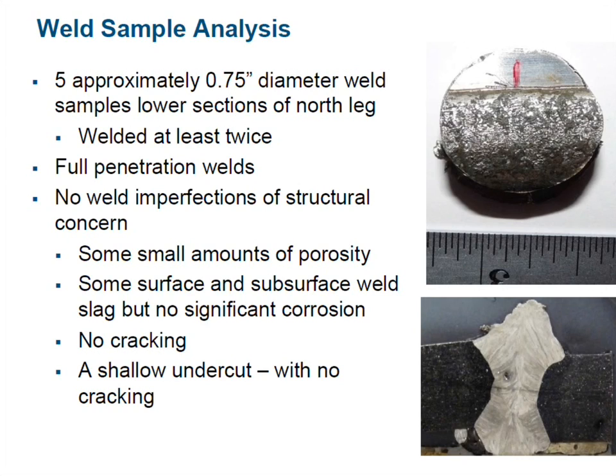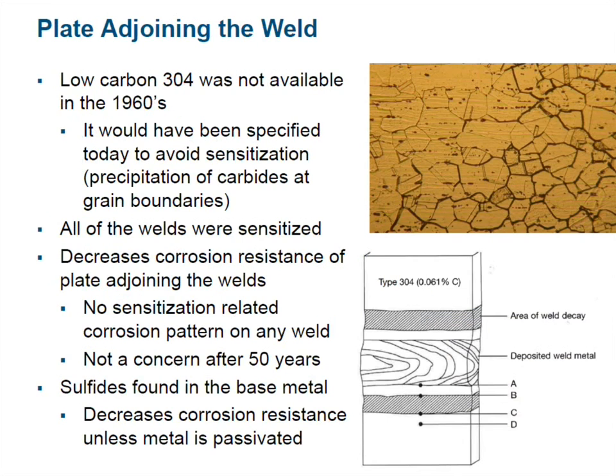These are the welds, or examples of some of the welds. They were all full penetration. As I mentioned, we had 5 samples, all 3/4 of an inch in diameter. There were no weld imperfections that caused any concern. Yes, there was some sensitization, which I'm showing a picture of here. Sensitization, when it causes corrosion, causes a classic band beside each side of the weld. Absolutely no evidence of that anywhere on the arch. If it hasn't occurred in the 50 years prior to this, when pollution levels were higher, then it's not going to occur in the future unless we have a dramatic change in the environment. So again, no concern.